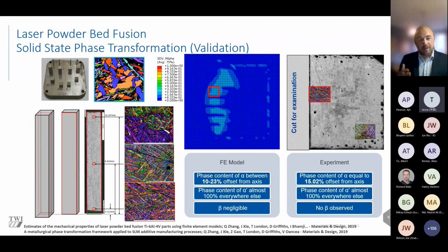And again, it's great to translate things like continuous cooling diagrams or time temperature transformation kinetics into our finite element models or simulation methods, but we've got to validate that, because a lot of those diagrams and kinetics were made for cooling rates not nearly as severe as we see in additive manufacturing. For those familiar with titanium alloys, this isn't a very pretty picture of a titanium alloy. It's an incredibly fine-scale martensitic structure.